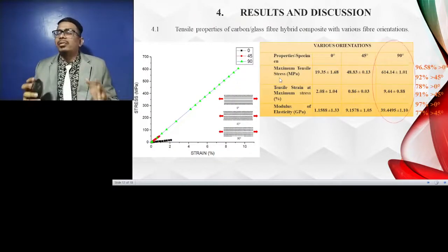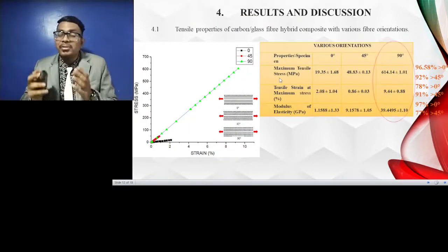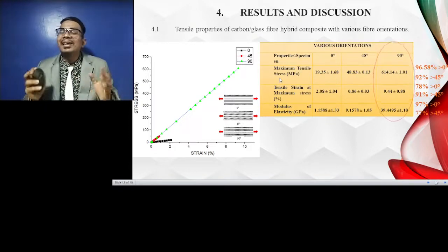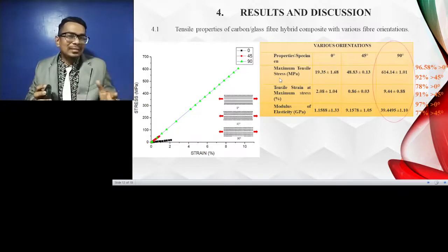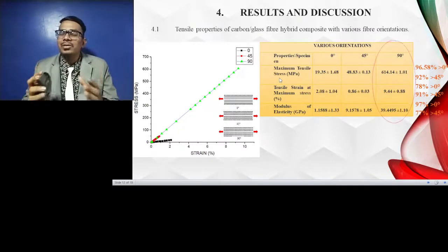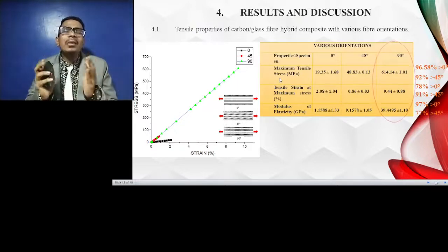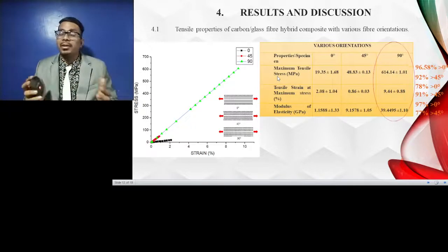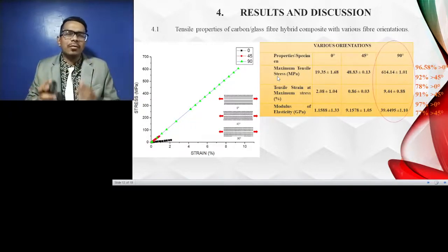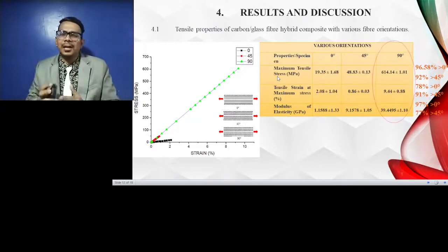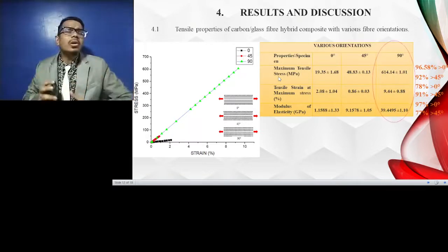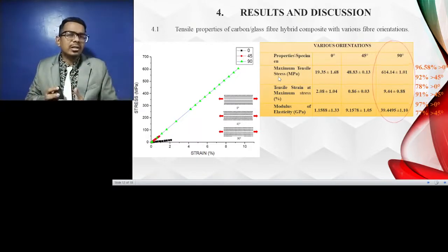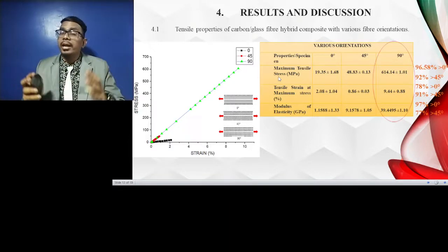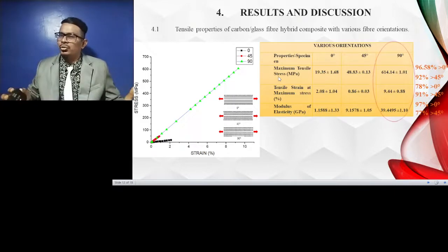Now let me look at the results and discussions. Ladies and gentlemen, based on your knowledge, which orientation do you think will give a great tensile strength? This data clearly shows that the 90-degree orientation recorded the highest values in all the results. The 90-degree orientation recorded the maximum tensile strength because the orientation is perpendicular to the direction of the force applied. Thus, it withstands the larger tensile strength, while the 0-degree orientation recorded the lowest because it is parallel to the force applied. Moreover, a higher modulus of elasticity was also found in the 90-degree orientation. From the graph, the modulus of elasticity also recorded large differences because of the various orientations used.